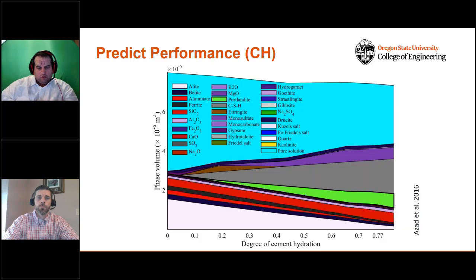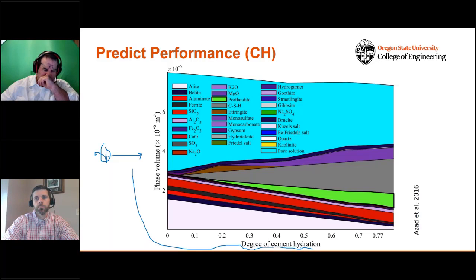Now, as I mentioned earlier, we've been developing computational programs that we think give us a lot of power to look at these systems and dive into them in great detail. This is a technique called Gibbs energy minimization, and it's a thermodynamic modeling technique. What we do is essentially take all the atoms and all the molecules and throw them into the pool. Then we let them react and see what happens over time. This is degree of cement hydration. The really powerful part of this is we can put cement, fly ash, slag, anything we want into the system, and we can see the reaction products that form.